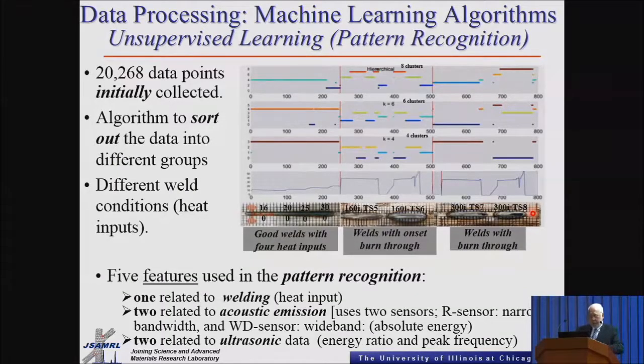Now, having obtained all the data, we wanted to do some assessment and processing of the data. For that, we used some type of machine learning algorithms to do pattern recognition, and initially collected approximately 20,000 data points. Again, we used these algorithms to group the amount of data points that we had collected, the different weld conditions, as a function of the heat input.